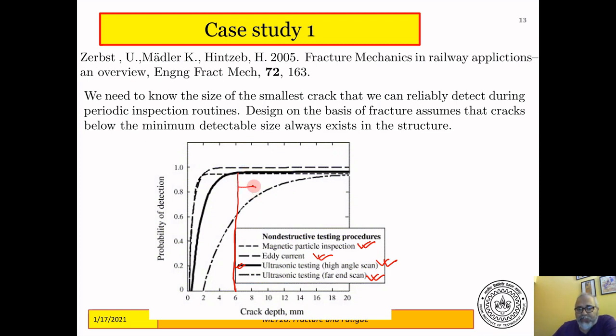So anything above 6 millimeters would definitely be detected if you are doing ultrasonic testing. Now, in that case, when I do a fracture mechanics based design, I should always assume that there are defects of the size equal to or less than 6 millimeters in the structure. So that is the starting point of my fracture based design. If I do something better, like magnetic particle detection, then I have a 100% probability of detection if my crack is, say, 3 millimeters. And in that case, I have to assume that the structure always has cracks of the size 3 millimeters or less in it. And then I have to ask those 4 questions, whether these cracks can grow, how fast they will grow, whether they can be stopped, and so on.